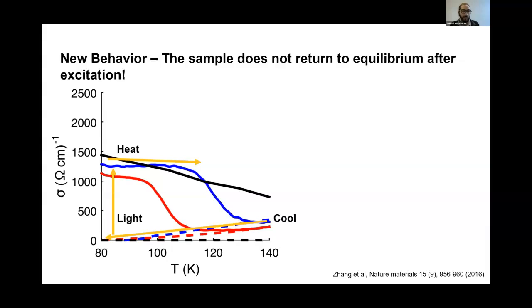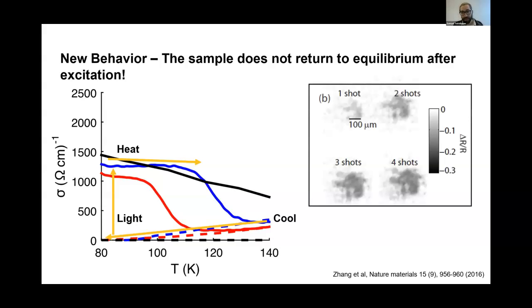So what we can do is essentially, photoexcitation is taking us permanently from the insulating state to a metallic state. And then heat is annealing away this photoinduced metallic state and taking us back to the insulating state. And if you look at the sample under a microscope, if you just look at the optical reflectivity over here, this 100 microns is about the size of our laser spot. And you can see this dark spot after one laser shot showing up. And after 2, 3, and 4 laser shots, this dark spot gets a little bit darker.